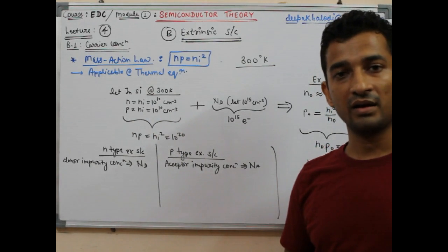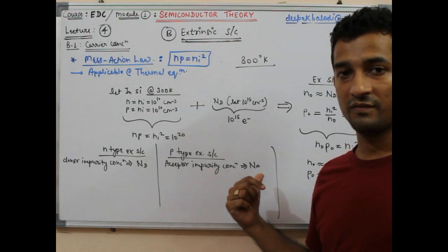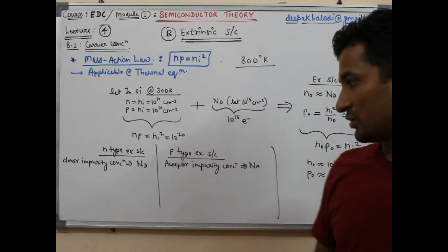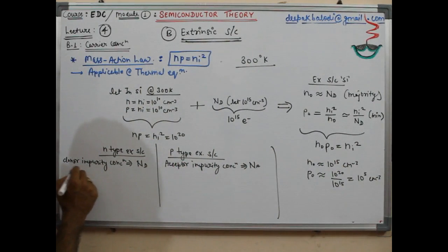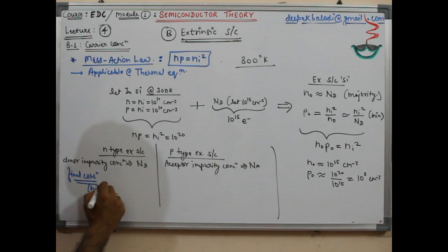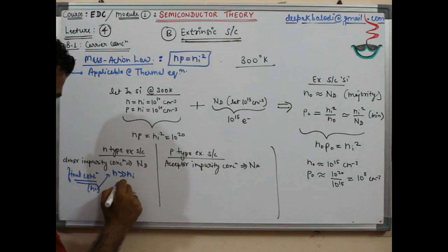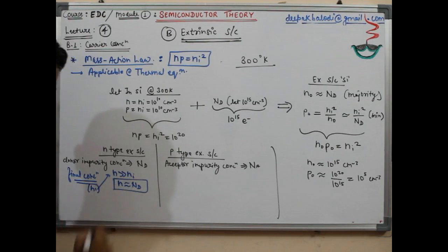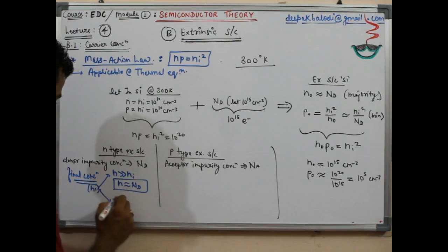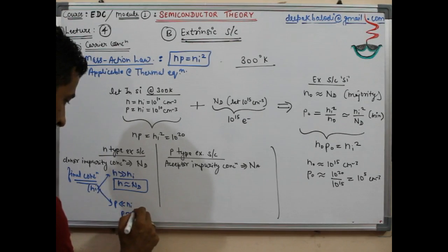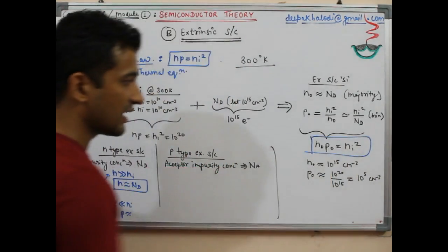Similarly, in this case, there are external holes, or impurity holes, the holes which are provided by the impurity, which are externally inserted. So when this case happens, the final concentration, initially it was ni, so finally n reaches much, much above ni, and now we know the value, n is approximately Nd, because we expect that a lot of additional carriers have come. Similarly, p goes well below this, and we have seen that approximately it is given by the mass action law, ni square by n.